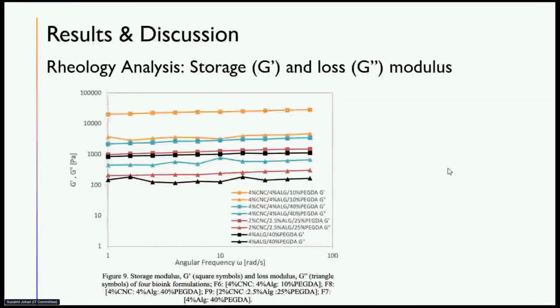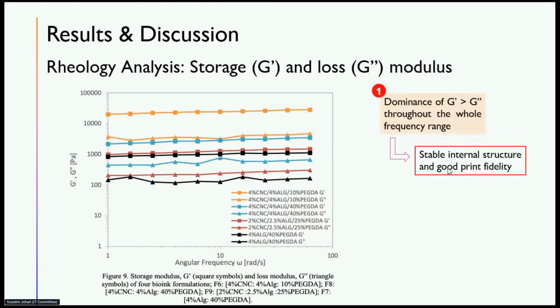Next slide. And the next part, the second rheology analysis, is the storage and loss modulus. The storage modulus is the square symbols, while the loss modulus is the triangle symbols. We can see that throughout the whole frequency range, the storage modulus is higher than the loss modulus. So this indicates that the gel has a stable internal structure and good print fidelity. Print fidelity is important because we want the printed construct to be as close and as accurate as possible to the construct that we design.